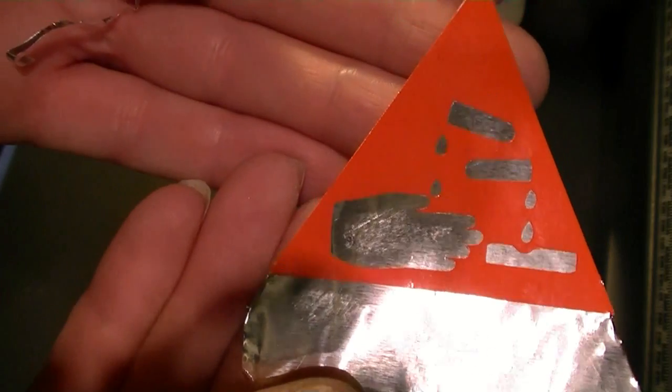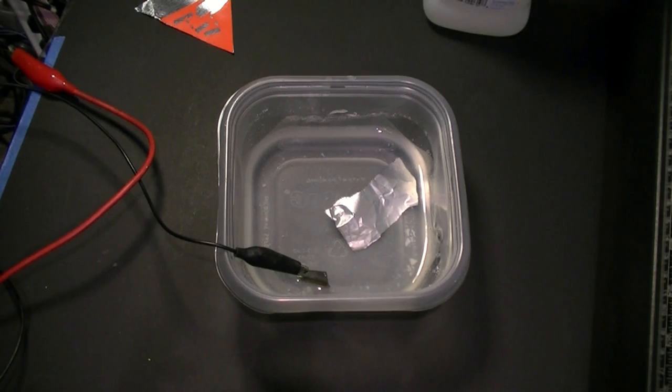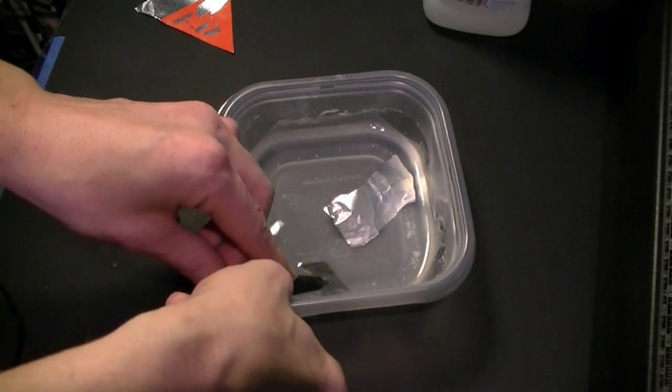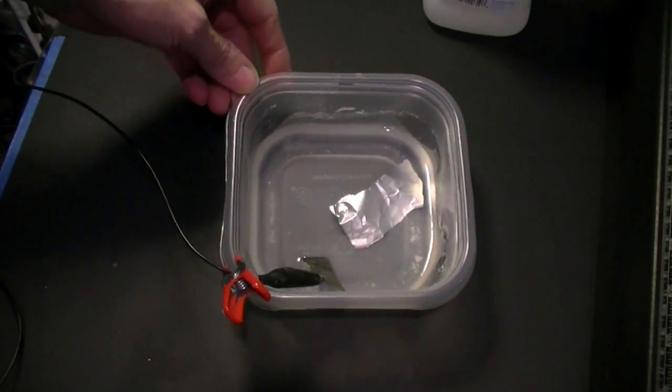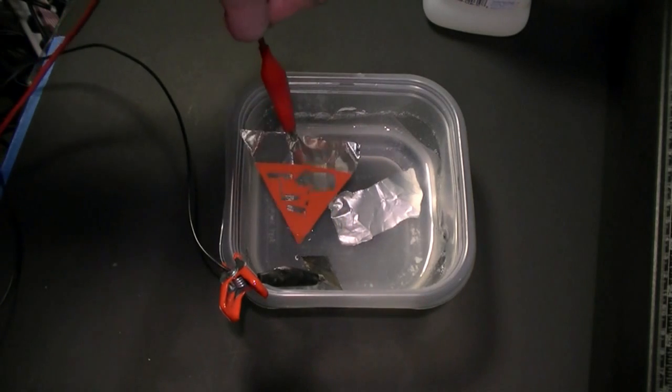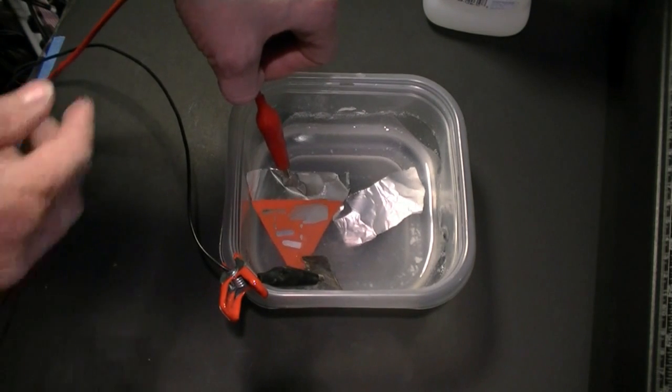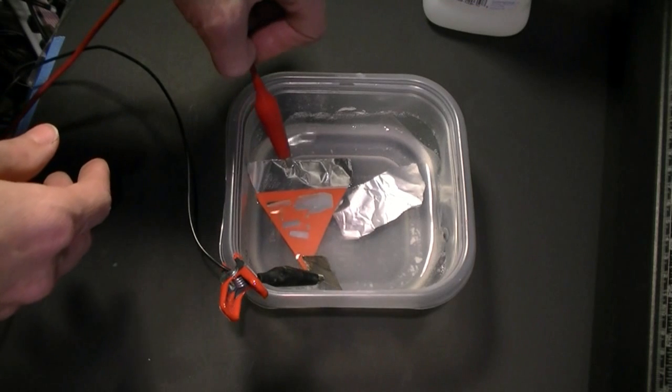The bath is a saturated solution of boric acid and water. I'm using a rusty razor blade for the cathode and the anode will be the workpiece, the positive side. The supply current was 20 volts and limited to 1 amp. The etch time took about 15 minutes.